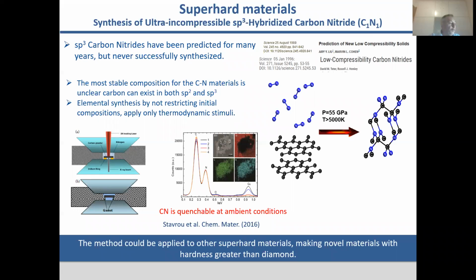And I think right now a lot of people discuss ternary compounds, including boron and so on. What I would like to highlight in this case is that this compound was stable at ambient conditions, so it was metastable, and this helped us a lot also to perform XRD and nail down the stoichiometry. So although the synthesis conditions are kind of extreme, the metastability gives us hope to apply this procedure in other materials.